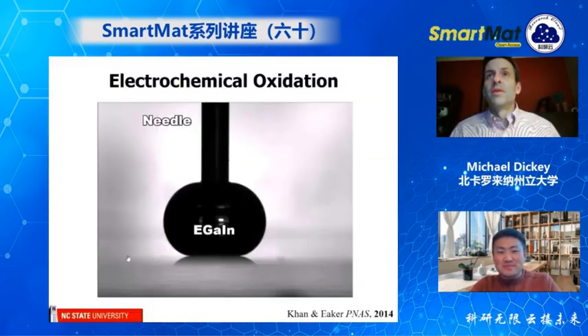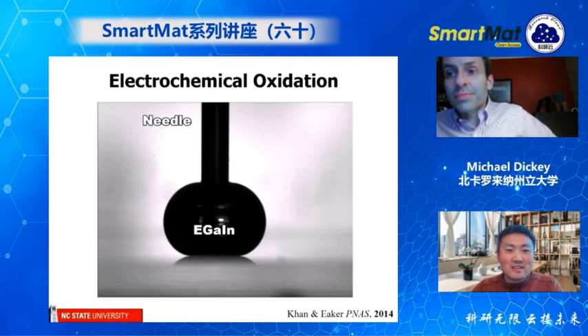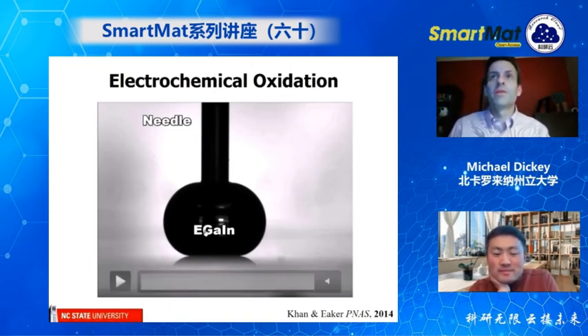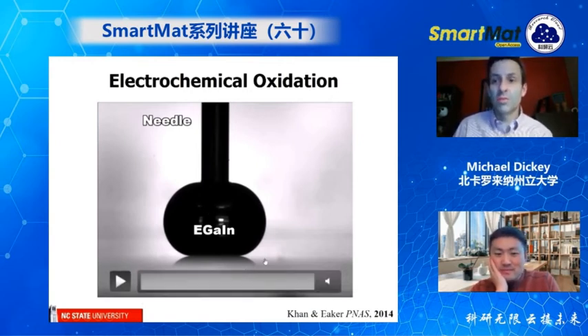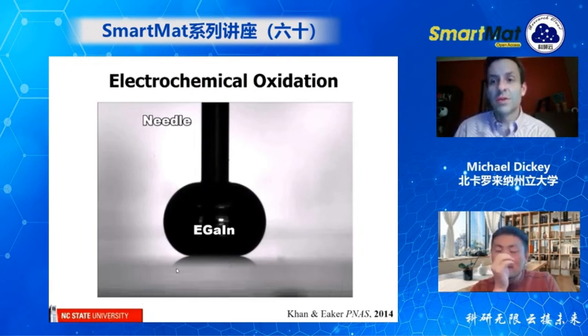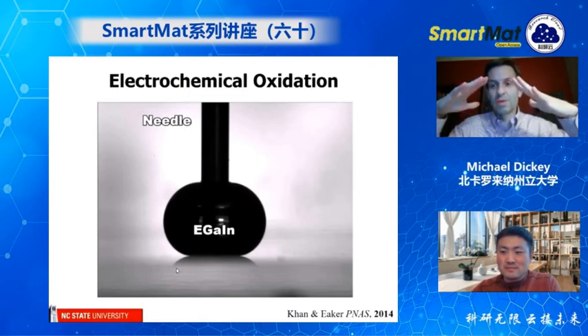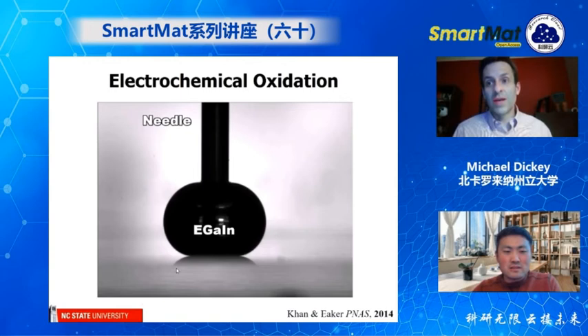Thank you. In traditional electrowetting, you apply a voltage between your liquid and your substrate. And typically you put an insulator on your substrate to avoid chemical reactions from occurring. That's what's called electrowetting on dielectric. When you apply the voltage, droplets can change their contact angle and wet more. What you're fighting against is surface tension. Surface tension wants it to be a perfect drop, and when you apply the voltage, it will spread out.